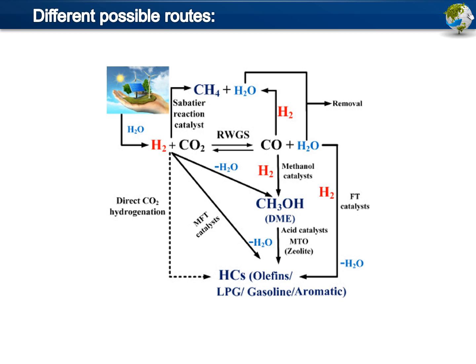We have different types of catalysts from the transition metals — for example, cobalt, iron, nickel, copper, zinc, and zirconia. We can use these different catalysts to reduce CO2 into useful products. Each catalyst has its own specialty and produces particular products: in the case of cobalt, the major product will be paraffins, and in the case of iron, the major products will be olefins. For cobalt, a major byproduct is also methane, which is less desirable compared to the hydrocarbon olefins.